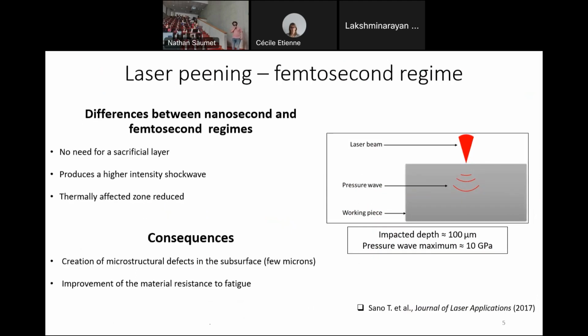So here we are working on femtosecond regime laser peening. The main difference is that there is no sacrificial layer needed, that it produces a higher intensity shock wave, and that the thermal zone is reduced compared to nanosecond. The consequences are the creation of microstructural defects in the subsurface within the depth. The impacted depth is a few hundreds of microns, or a few tens of microns.